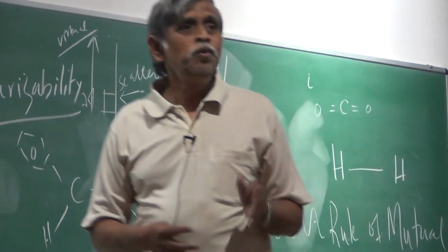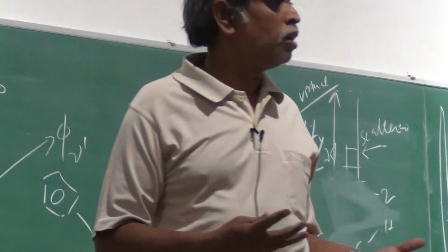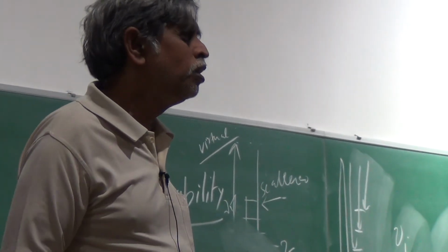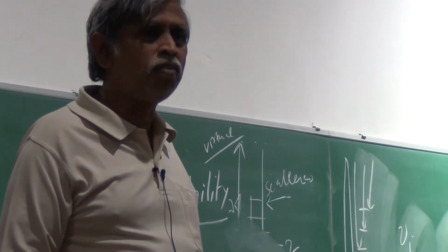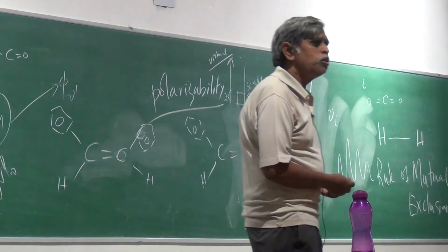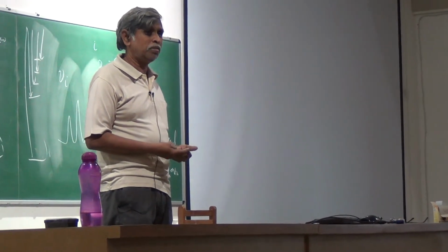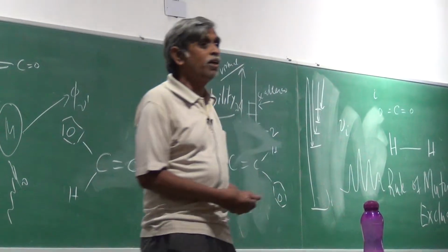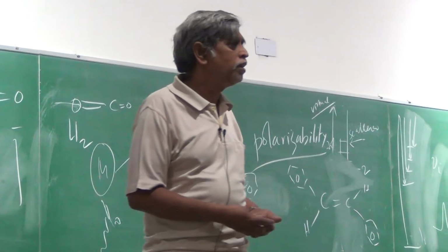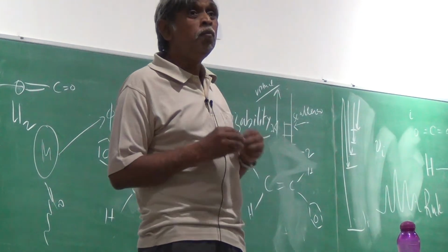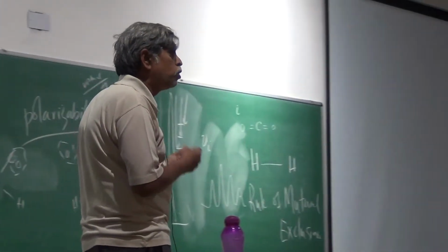So what do you do? You take a wavelength in which the molecule does not absorb and therefore cannot give you fluorescence. So you're going to sort of trick the molecules. You give them frequencies or wavelengths of light that are inappropriate for an absorption emission process. Now, most organic molecules will absorb at 3, 4, 500 nanometers. Give them 750 nanometers. There's hardly any state for absorption in many molecules. Some molecules do have states even at that, but most will not have an absorption at that point. So if they don't have an absorption at that point, what's the only thing you're going to be seeing? Raman.